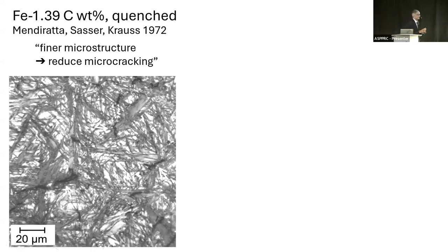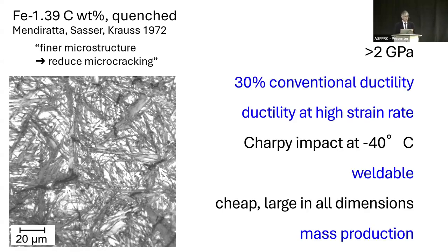And again, I'm paraphrasing here, but there was a clear statement that if I make my structure finer, then these cracks tend to disappear. And that had an impression on me, and I'm going to explain why. I want to create martensite, a high carbon martensite, which I quench and I do not temper. I want to get the full strength of untempered high carbon martensite.